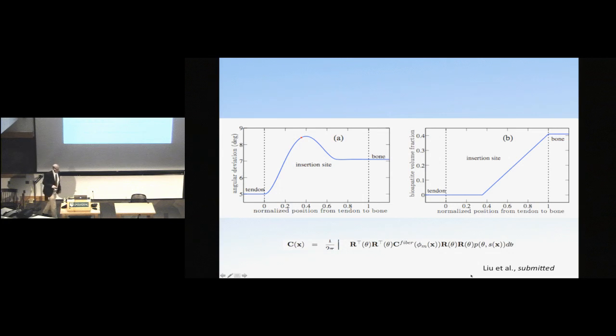Then this equation is cut off in this picture for some reason. This is meant to be an integral. On my screen, it's an integral over the unit sphere. And we take the properties that we estimate of each fiber, and then just do a normal tensor transformation weighted by a probability distribution over a unit sphere to get the actual stiffness tensor at a location along the material. And the stiffness tensor is what determines how stresses are distributed.